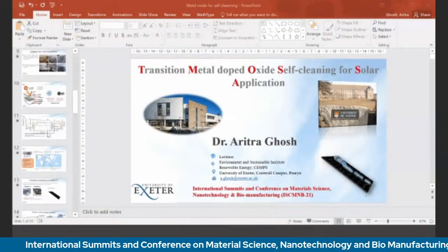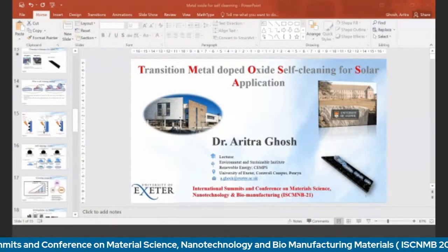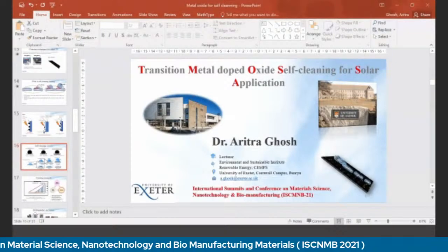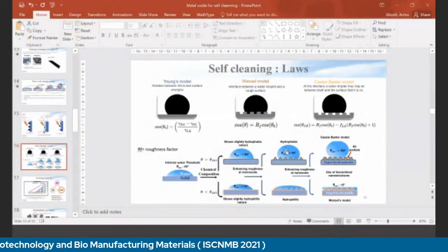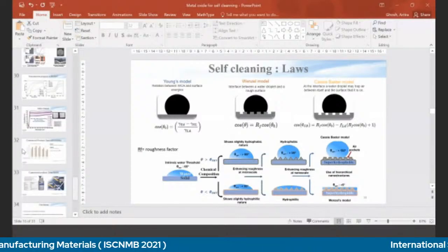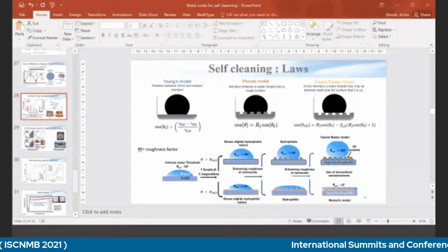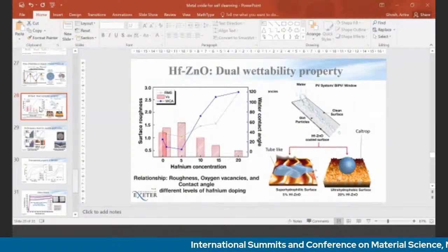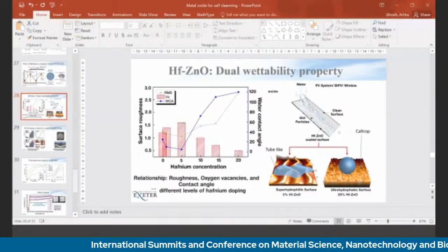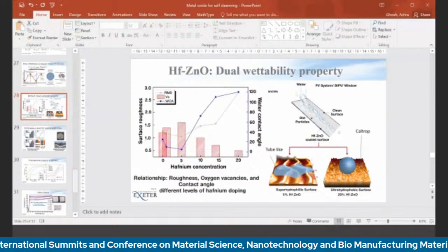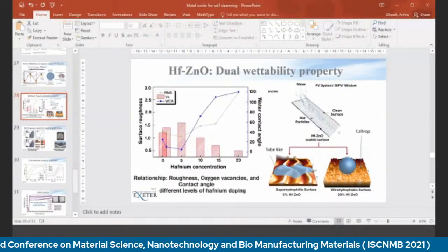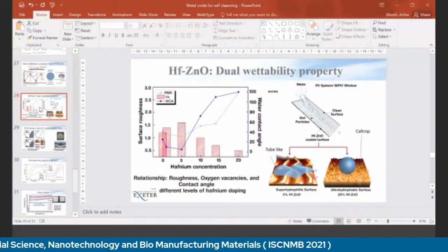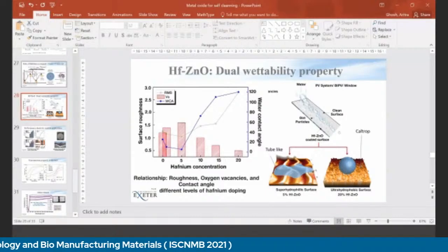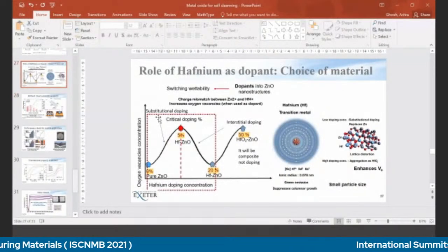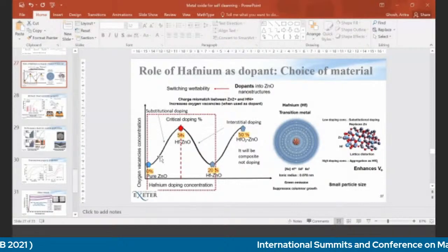Yeah, you can explain this property by using the Cassie-Baxter law, or you can change the roughness. And right now, what we did here, we changed the roughness by increasing the doping agent. We employed the hafnium, and as hafnium has a different property, when you are giving the 5% doping with the zinc oxide, you are doing substitutional doping here, and then your surface roughness is a bit different.